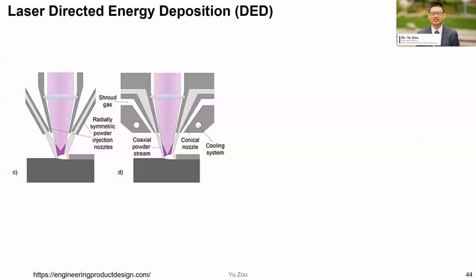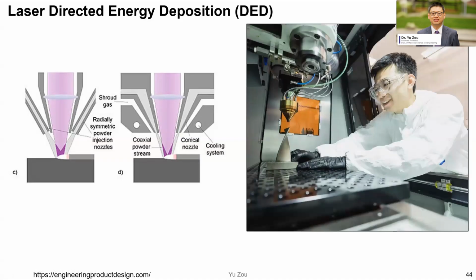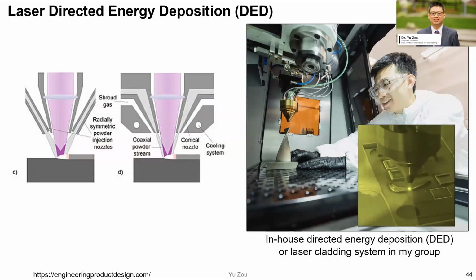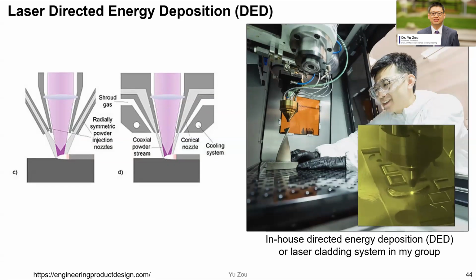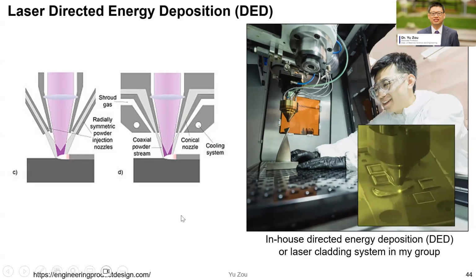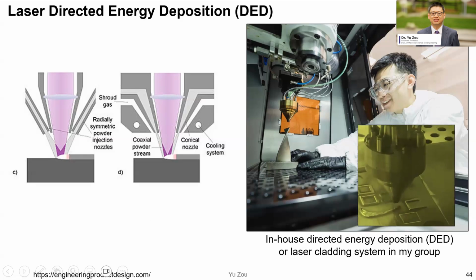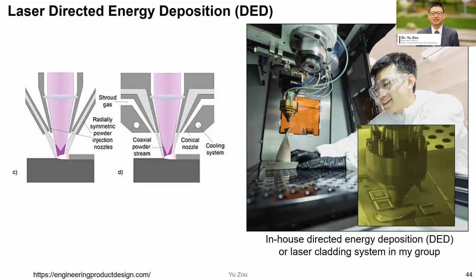Okay, so I'm going to quickly talk about another technique we call direct energy deposition. In our lab, we typically use a laser as the energy source. Basically, the laser and the powder go to the same spot, and then the laser melts the powder, and then layer by layer, we can build up a large part. This is our in-house laser DED system. So you can see we can use the laser to melt the metal powder in a specific location to make parts.